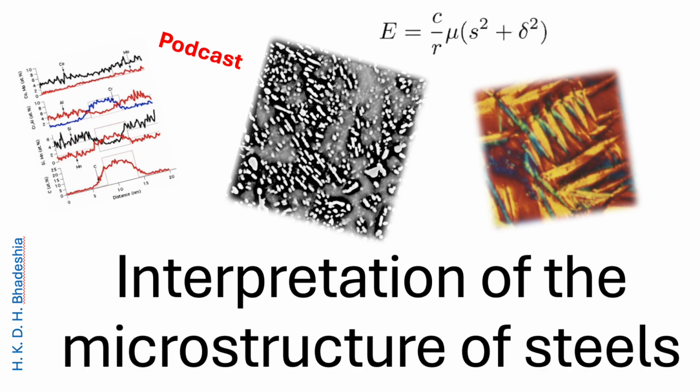The displacive mechanism, the military path. This is the displacive approach. Instead of breaking bonds and allowing diffusion, the crystal structure changes through a homogeneous deformation of the parent lattice. A deformation. Yeah, imagine forcing the FCC structure into the BCC structure by squeezing and shearing it, all while keeping the relative order of the atoms. It's entirely diffusionless. Diffusionless, so everything happens almost instantaneously. Instantly. No time for elements to wander off.